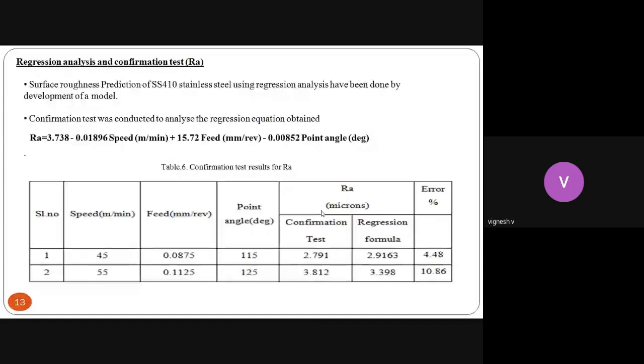So after the Taguchi analysis, I also conducted a regression analysis using the Minitab software. The main reason for conducting the regression analysis is to get a prediction model, that is, a prediction regression equation. When we get that regression equation, and when we use some values of speed, feed, and point angle, we can predict the roughness value in the machining operation. So if we randomly take some speed, feed, and point angle, we can predict the roughness value. That is the main thing we can get using this regression analysis and prediction model.